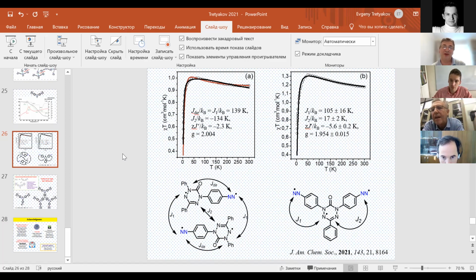This is very interesting, but we did not concentrate on studying sublimation. Your systems are also interesting from this point of view, because as they are complex, I assume that the crystallinity is not so good sometimes, because you have a very strong complexity from the chemical point of view, and probably the crystals grow better with simple molecules than with big molecules like you are preparing. I don't know if this is true or not. Do you observe that your crystals are small or not? Yes, we observed formation of very small crystals. Yeah. Then it's not possible to compare with crystals growing from solvent. But from sublimation, it is a good thing. Then you have interesting systems.